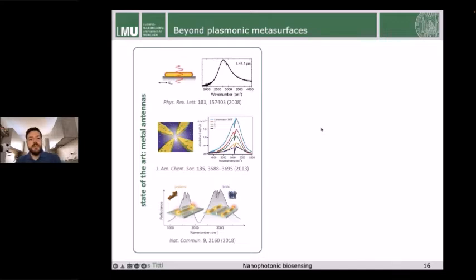Now, when you employ them for infrared spectroscopy, for surface enhanced infrared spectroscopy, the common technology here is gold nanoantennas of different shapes. So you see here these rod antennas, here some four antenna coupled system, or you can implement antennas of different lengths to simultaneously detect both the lipids and proteins in the system. But what you notice is when you look at the resonance of the antenna, this is actually very, very broad. In terms of wave numbers, this is several microns here, the range, so very broad resonances.